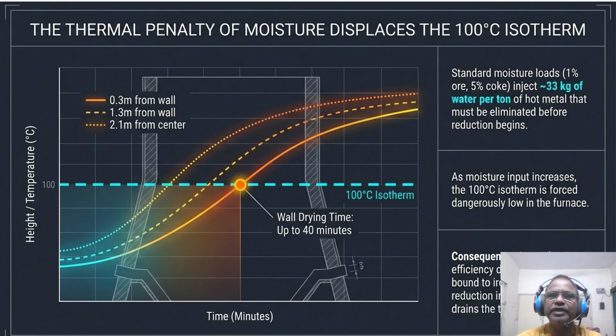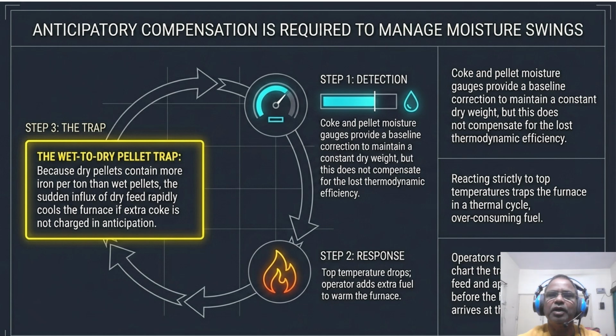This slide illustrates what I call the wet to dry pellet trap. Follow the circular logic from step 1 to step 3. Most operators rely on moisture gauges for a baseline correction to maintain a constant dry weight. This is necessary but insufficient because it ignores lost thermodynamic efficiency. So look at step 2. As top temperature drops, the instinctive reaction is to add fuel.